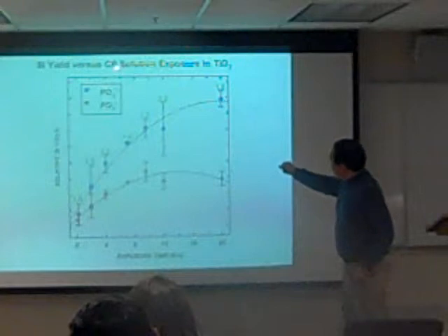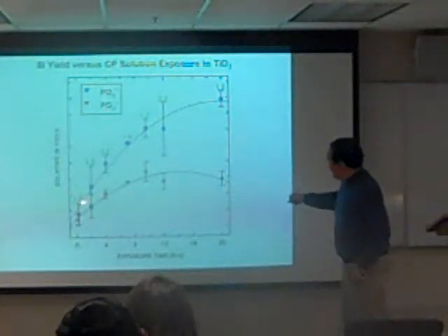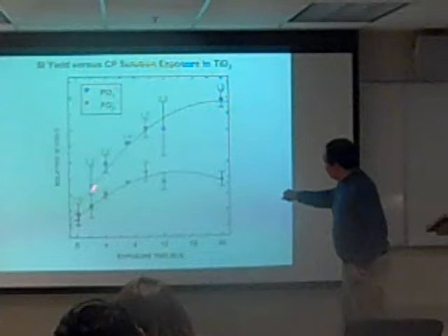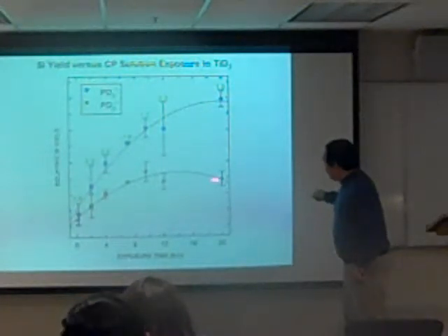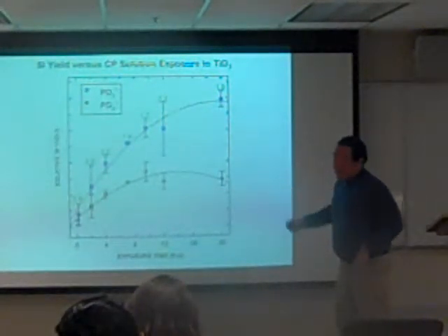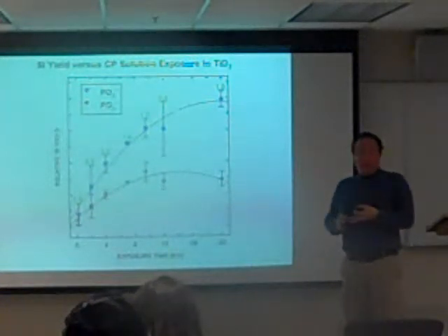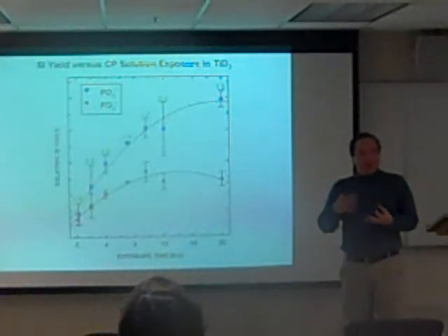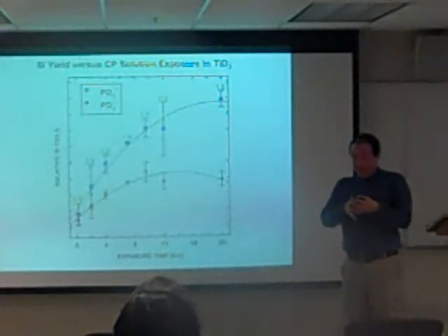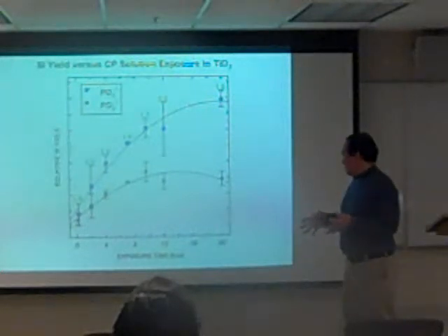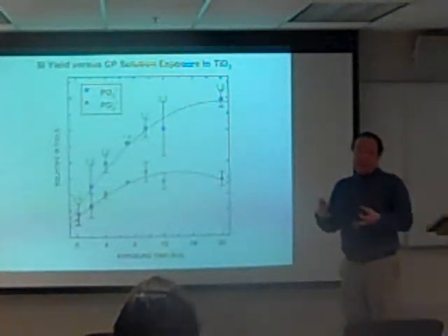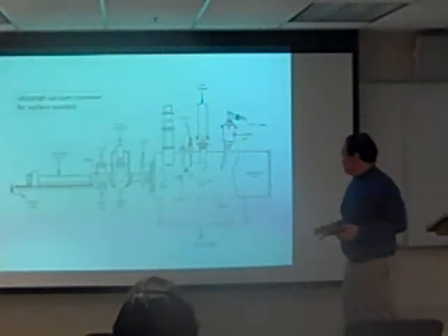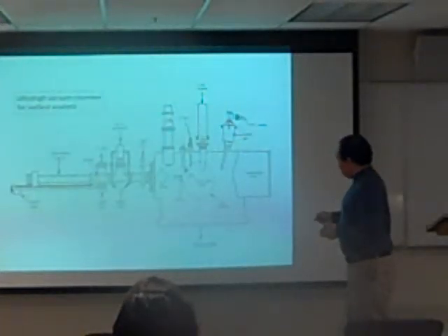And so this is the secondary ion yield when you expose the TiO2 to the phosphate solution. And then this is just the phosphite, this is the hypophosphite. These green numbers, they're basically the ratios. So it looks like the phase that is still amorphous, but it's closest to the brushite phase of the different phases that we surface analyzed, is the most thermodynamically unstable phase. That's something that's not surprising. So basically that was done in that.